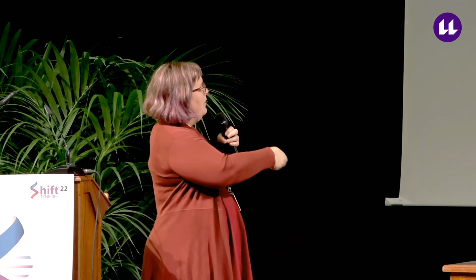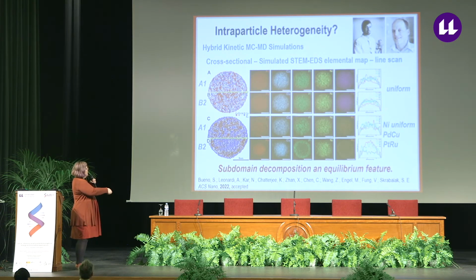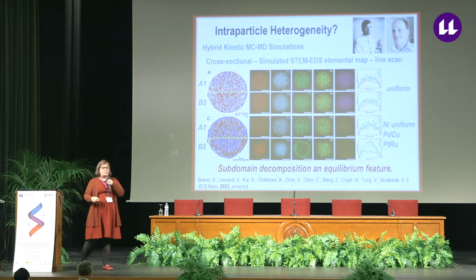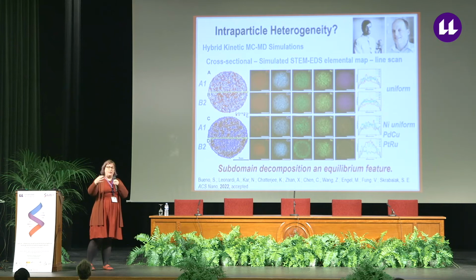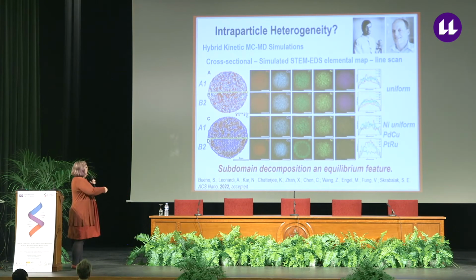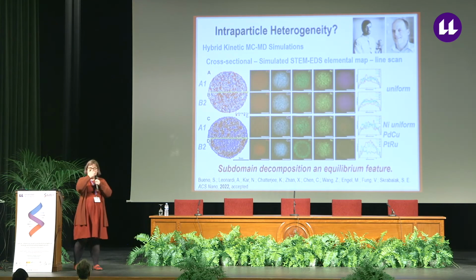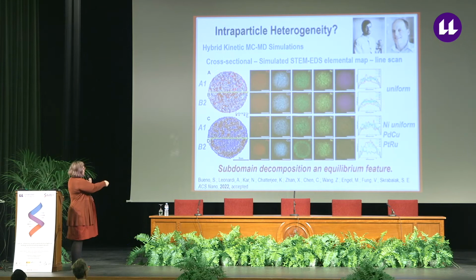And so shown here in the top half are the results for nickel, where experimentally you saw mixing at the atomic scale. And on the bottom are the results with ruthenium, where we observed that segregation or intraparticle heterogeneity. And so on the left here are cross-sectional views or slices of the atomic distributions after the simulations. And you'll notice on the top, all of the different elements appear to be well mixed. And this is regardless of if they started with palladium copper as an intermetallic or a random alloy crystal structure. There's good mixing at the atomic scale.